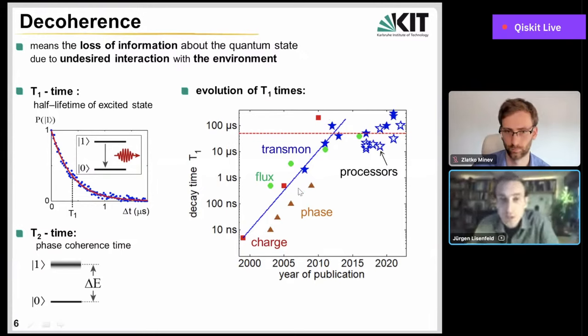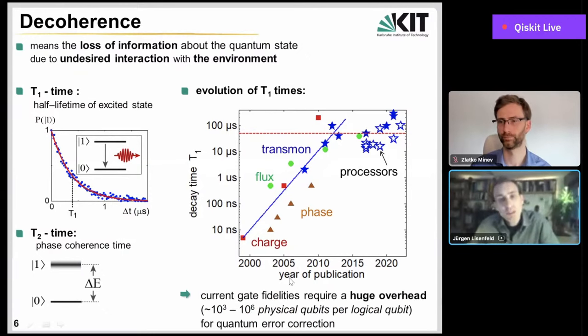This covers the development of the phase qubit in Martinis's group, the flux qubit in Hans Mooij's group, and also the transmon, which emerged from the charge qubit at Yale. You see the transmon is now the workhorse of this field. All the processors, these open stars, are being built on these transmon qubits currently. I have drawn this red dashed line here, which indicates that we may have hit some kind of hard wall already about 10 years ago. This kind of evolution seems to have stalled a little bit. It's much more difficult now to get better coherence times than it was in the gold rush years. This is unfortunate because at the current levels of coherence times, you would still require a huge overhead in the number of physical qubits to form one completely error-corrected logical qubit.